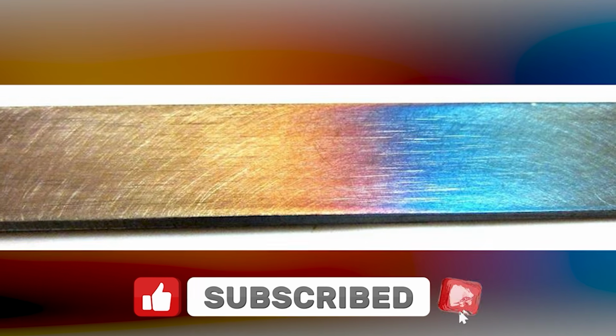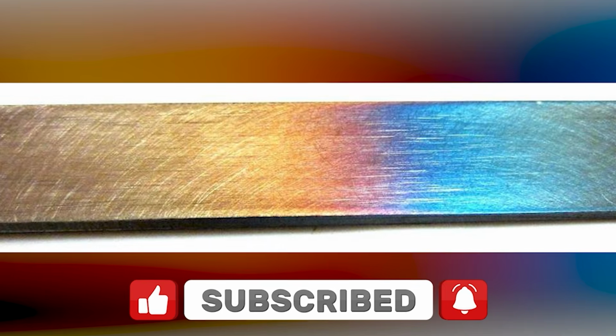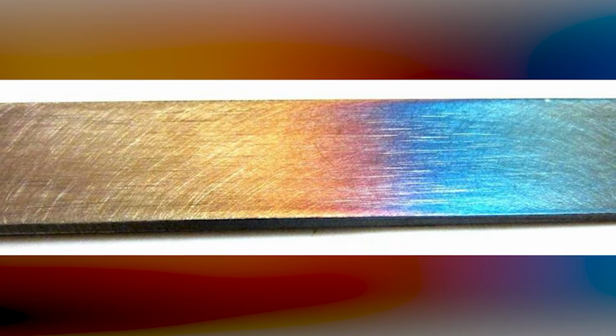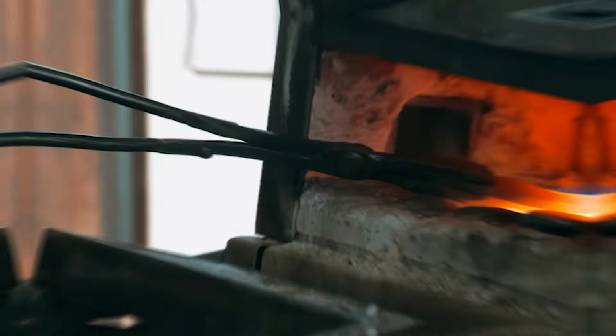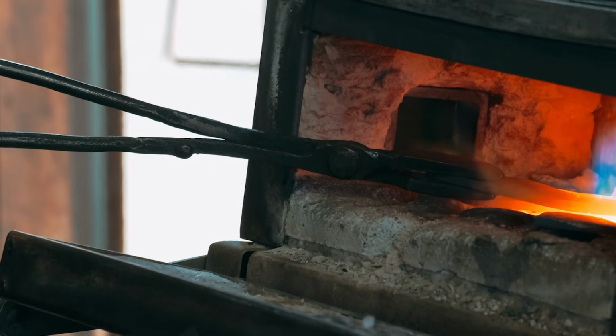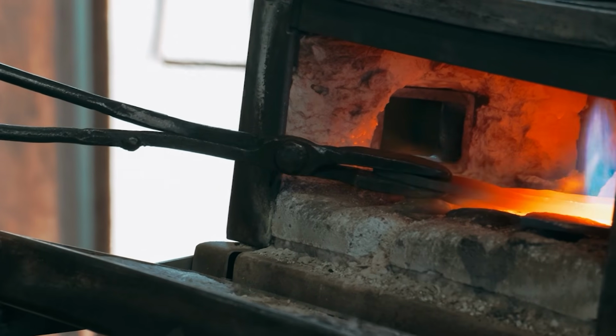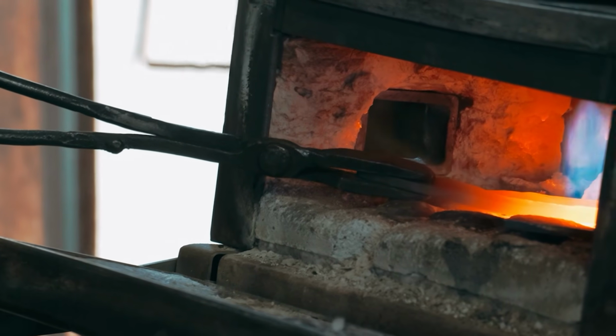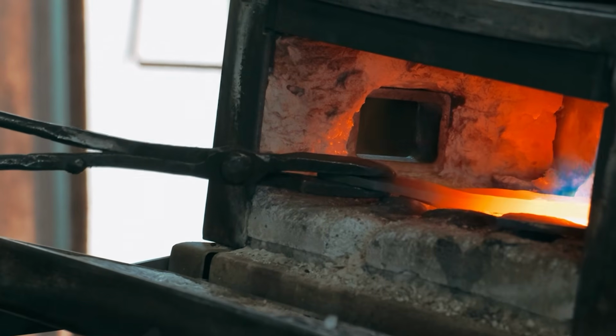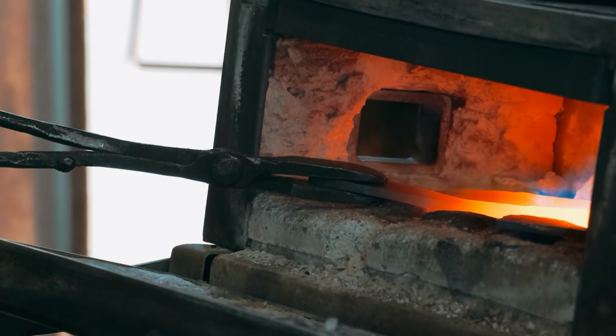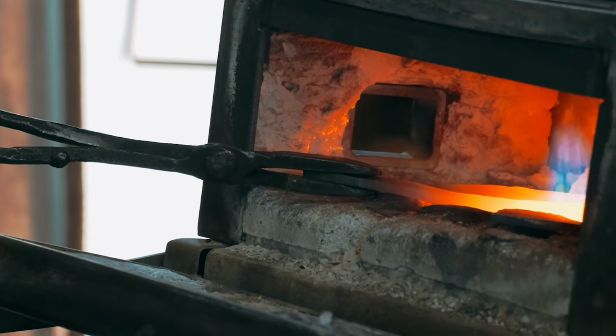Straw yellow, around 230 degrees Celsius, made steel perfect for cutting edges. Bronze, around 255 degrees, was ideal for springs and swords that needed flexibility. Blue, around 300 degrees, created tools that could absorb impacts without shattering. The smith would heat the blade until the desired colour appeared, then immediately quench it again to lock in that exact microstructure. He was manipulating crystalline transformations in steel using nothing but his eyes and experience.